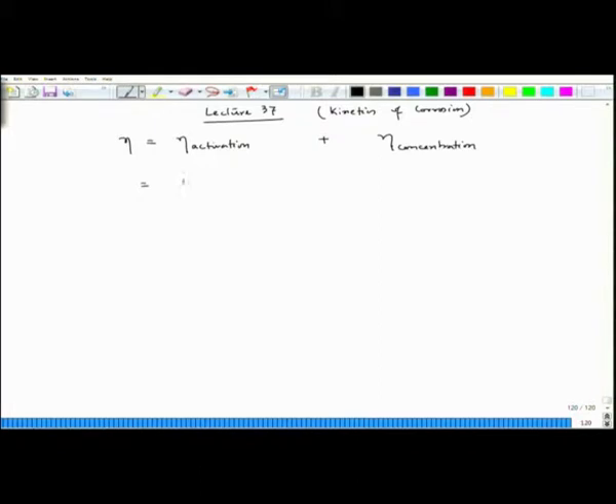can be related with beta log I by I0, and the concentration part can be related as 0.059 by n log of 1 minus I by I max. And this I max in different books is sometimes written as I max or sometimes as IL, which is nothing but I limiting, the limiting current density.